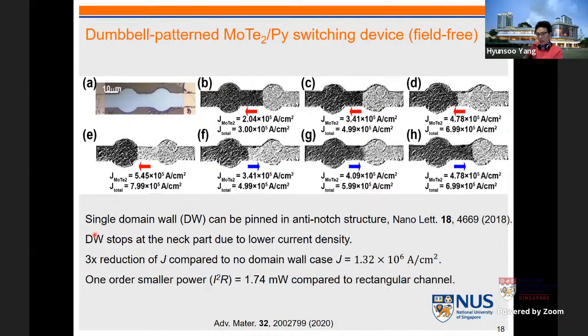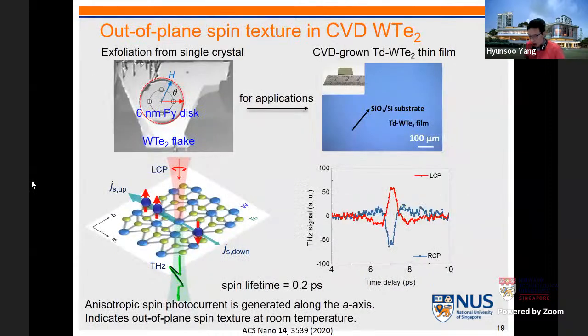This material is interesting not only for in-plane but also for perpendicular magnet switching, because it can generate the out-of-plane spin. If you look at the atomic arrangement of this tungsten ditelluride, you can see it's very anisotropic. For example, if you flow current along this b-axis, then you look at your atomic arrangement on your left side and on your right side from the perspective of electrons, you can see it's symmetric. That means the potential is kind of flat.